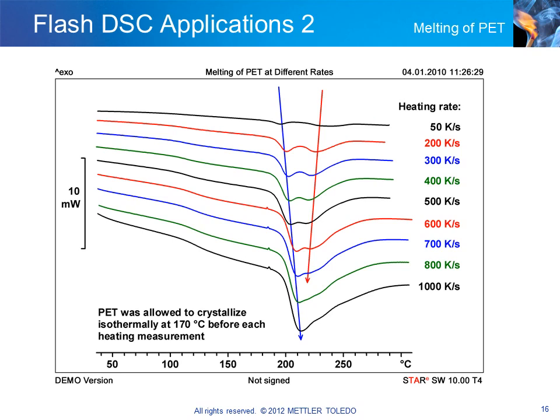The need for heating and cooling rates higher than those available with a conventional DSC is driven by potential applications. I would now like to discuss some typical applications. The diagram shows melting curves of polyethylene terephthalate, or PET as it is commonly called. The material was allowed to crystallize at 170 degrees Celsius for 5 minutes before each measurement. The measurements were performed at heating rates between 50 and 1000 degrees per second. The diagram displays several measurement curves that exhibit a double peak in the melting region. At higher heating rates, the low temperature peak is shifted to higher temperatures and the high temperature peak to lower temperatures.